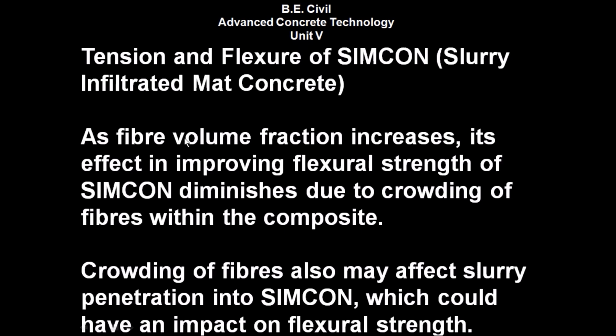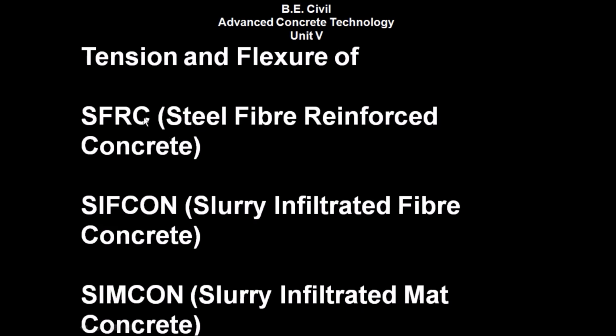As fiber volume fraction increases, its effect in improving flexural strength of SIMCON diminishes due to crowding of fibers within the composite. Crowding of fibers also may affect slurry penetration into SIMCON, which could have an impact on flexural strength. So we have seen the tension and flexure of SIMCON, that is slurry infiltrated mat concrete.